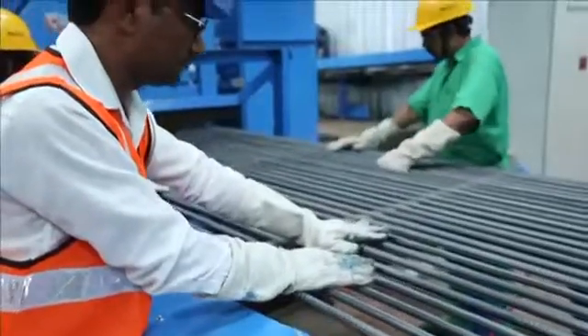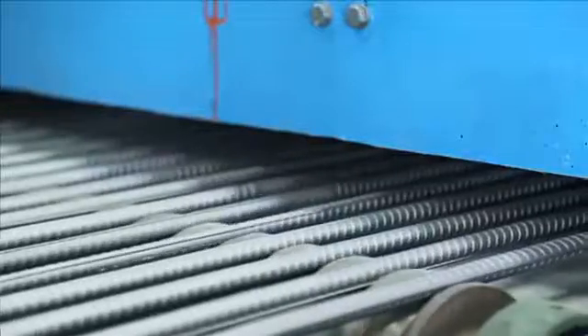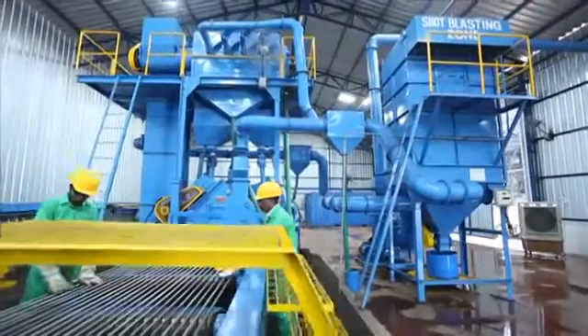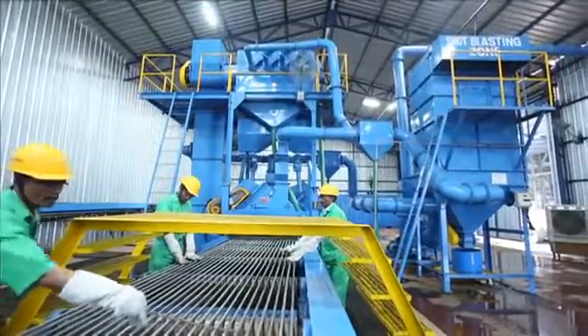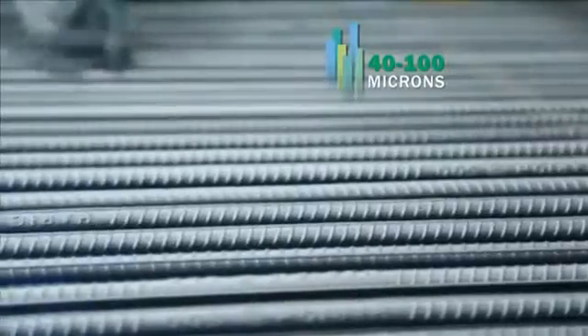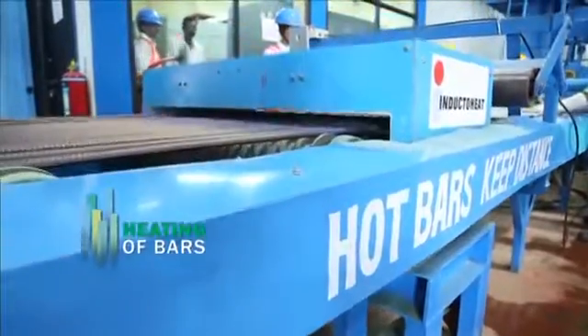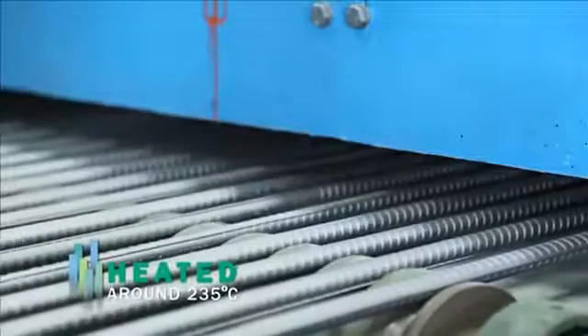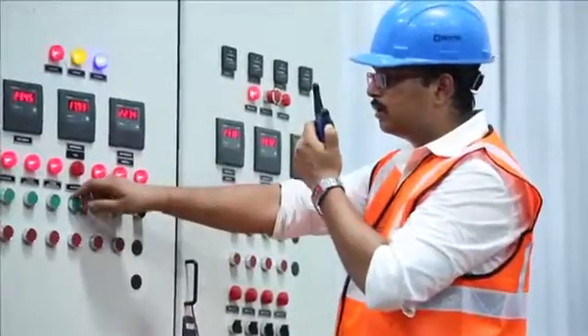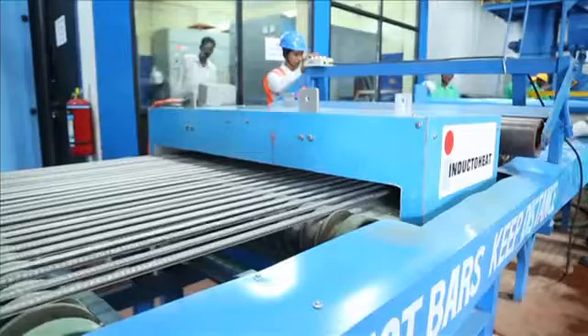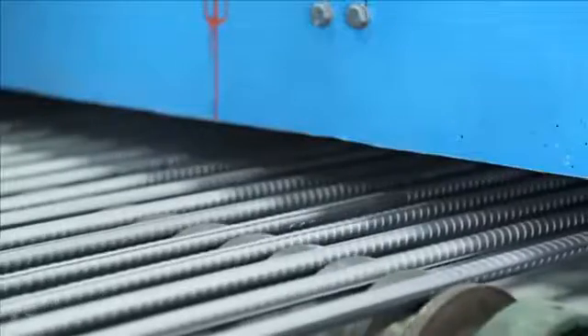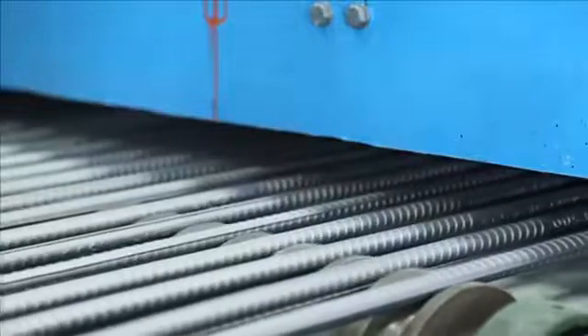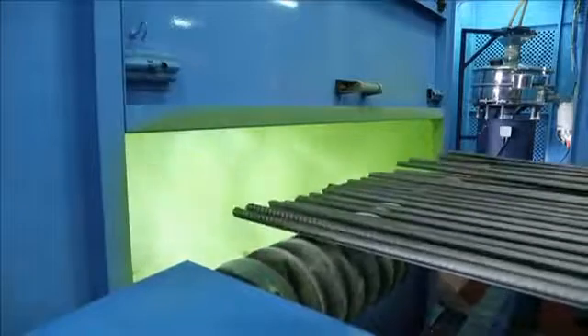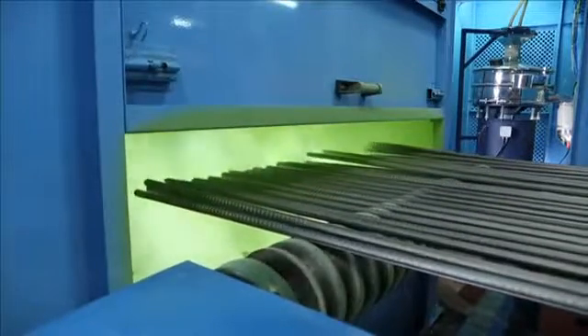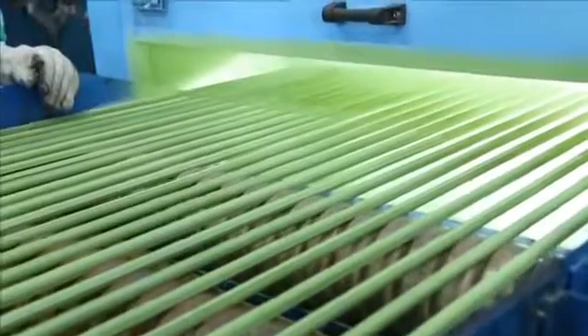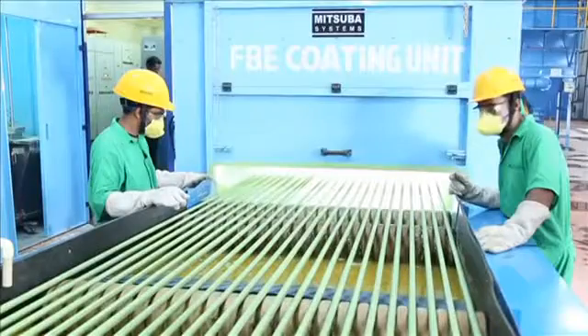The reinforcing steel is blast cleaned to a near-white metal finish using abrasive material in a shot blaster. The shots clean the surface of the bar and grits provide an anchor pattern of 40 to 100 microns to the bar surface. The next process is the heating of the bars. They are heated to around 235 degrees Celsius by passing them through an electric induction heater, followed by coating of the bars, in which the heated bars are passed through an epoxy coating booth, where epoxy powder is applied through an electrostatic process. As the powder leaves the gun, an electrical charge is imparted to the epoxy powder particles. These electrically charged particles are attracted to the grounded steel surface, providing a uniform coverage of the coating.